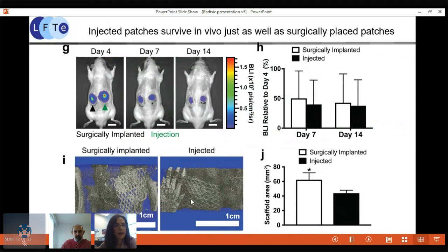In this particular case, surgical implantation under the skin involves cutting the skin flap and placing the scaffold, nicely opening and lining it under the skin and suturing around it. Whereas injection just involves pinching the skin, injecting some PBS first, and then injecting the scaffold under the skin in this puddle of PBS. Also, using micro CT of a scaffold that was labeled, we can see that the scaffold does indeed fully open up after injection, as these two areas exhibited some, although rather small, differences in area of surgical implantation versus injected.